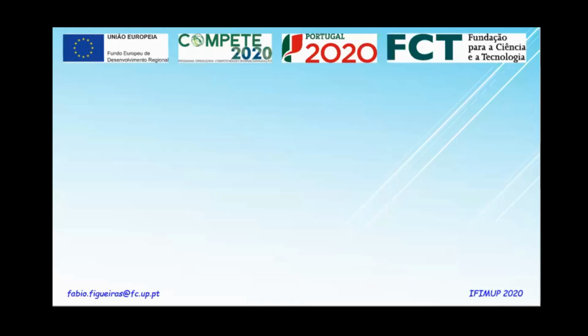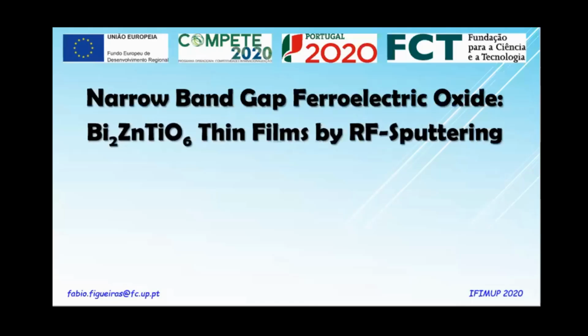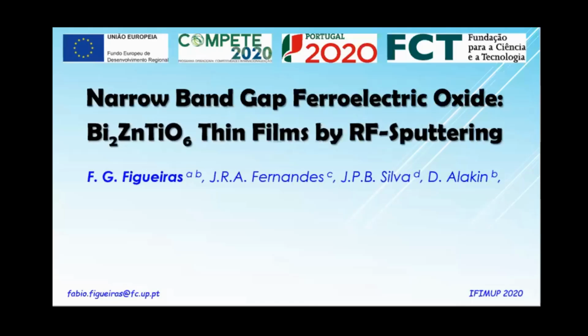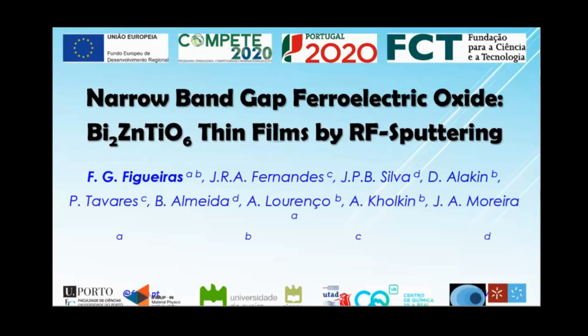Here I'm presenting a new material called double perovskites made of bismuth, zinc, and titanate. And as an oxide, it is a really interesting material. The point is that this material, as an oxide, has a narrow band gap. Usually perovskites, like bismuth ferrite, and others will have a very high band gap. And why is this interesting? Because as you will see now,